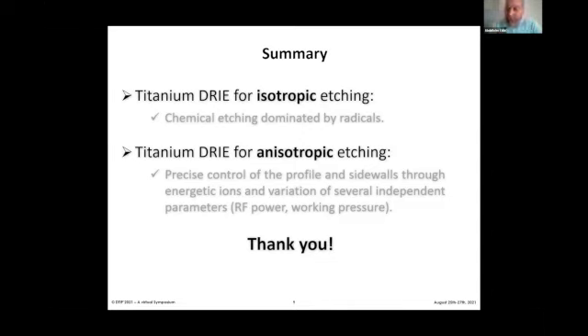I have a small question, just the substrate that you etch, how do you prepare your substrate? Well, the substrate used is bulk titanium. We use commercially available grade 1 titanium wafer, and I cut the wafer into different samples. So that's why I will just show you.